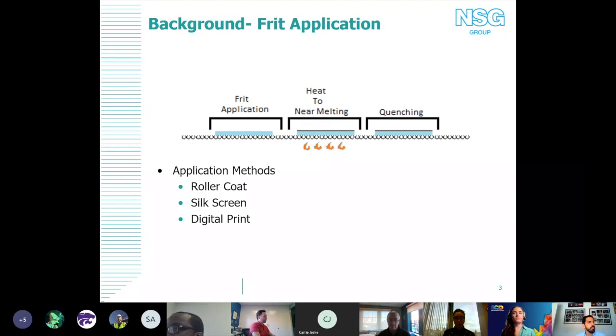At the fabricator's location, they apply a frit. They could apply it through a couple different methods: roller coating, screen printing, digital print. Kate probably knows there's others that I maybe didn't mention, but generally the frit is applied onto the surface of the glass. And the frit has these glass particles or ceramic glass particles in it that after it's applied, you put it into your tempering furnace, and it's heated to a near melting temperature, not quite melting, but enough that